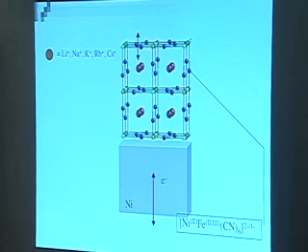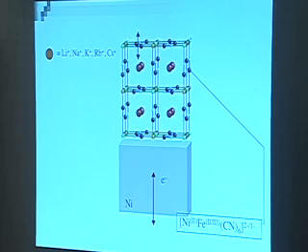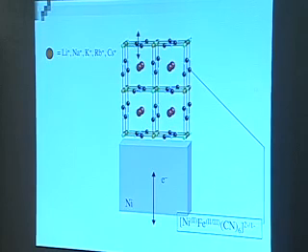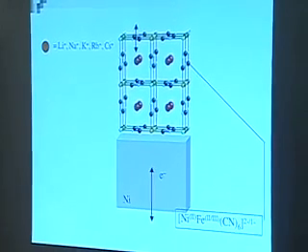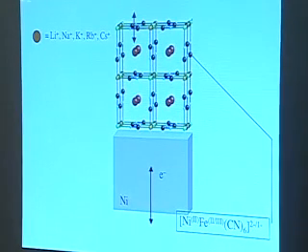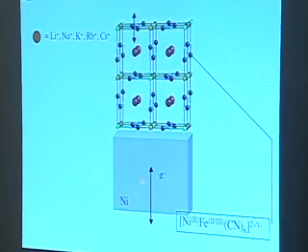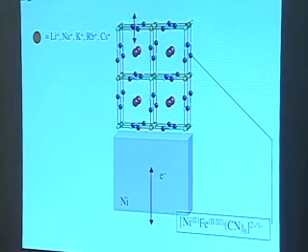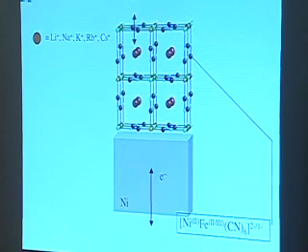Now, why is that? The reason to do this is that nickel is a fairly inexpensive material, fairly catalytic material, a lousy electrode material for oxidations, very good for reductions. Okay. Why is it lousy for oxidations? Because it would rather make nickel ions than do anything else. So you just corrode your electrode away if you try to do oxidations in aqueous electrolyte.